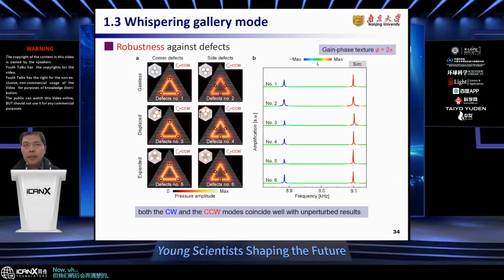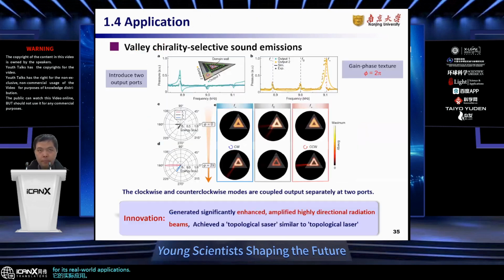Now, let's talk about how robust the system is. We simulate defects in the corner or side regions, and we see that the frequency and the amplification of both the counterclockwise and clockwise modes are still pretty much the same as when there are no defects. So our theory stands very strong, even when we introduce defects. That's really a good sign for its real-world applications.